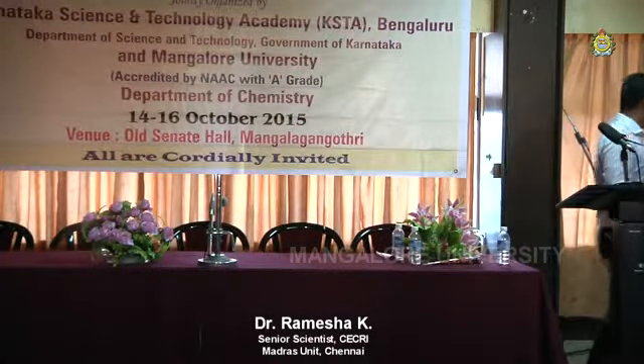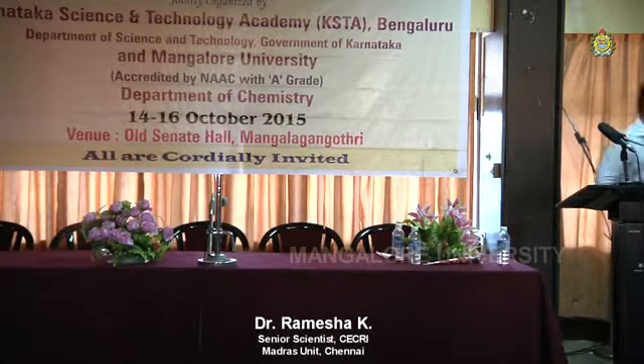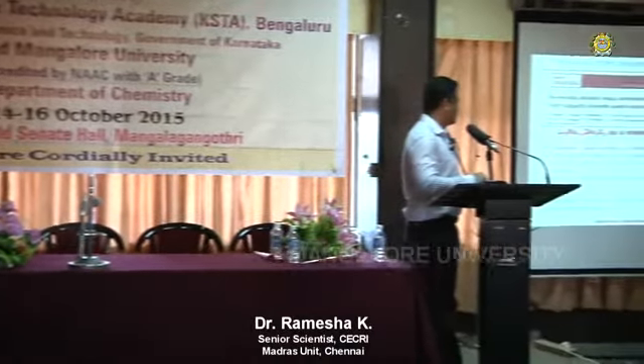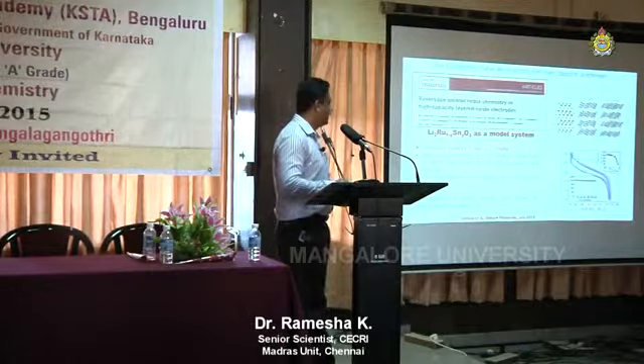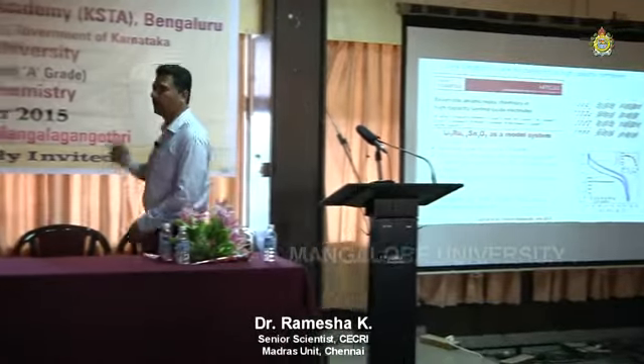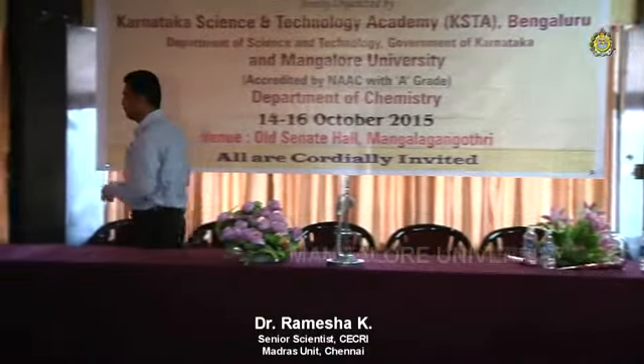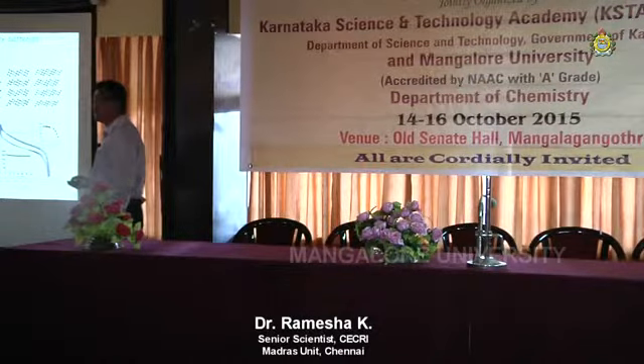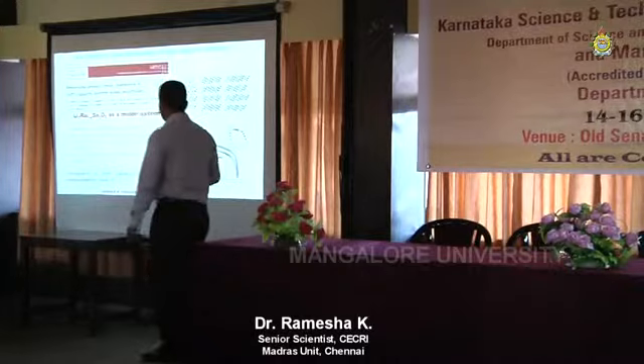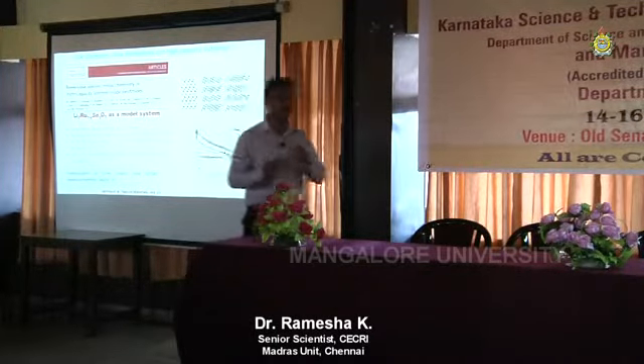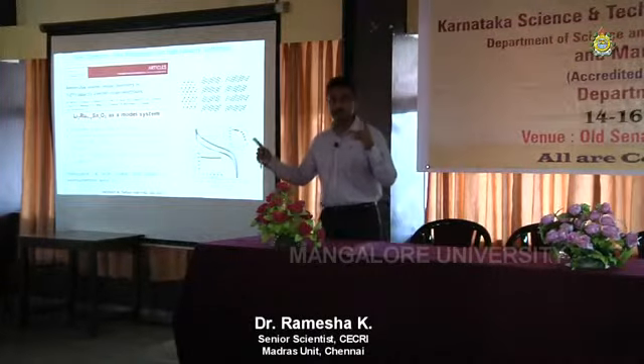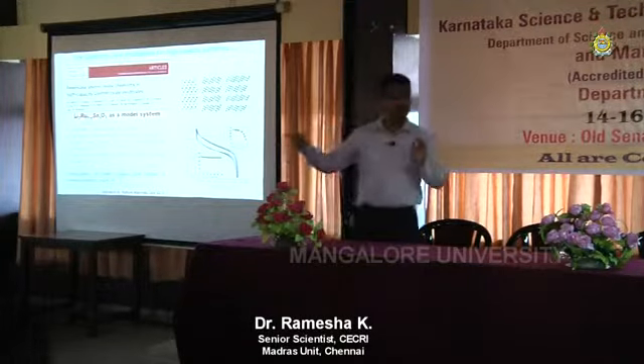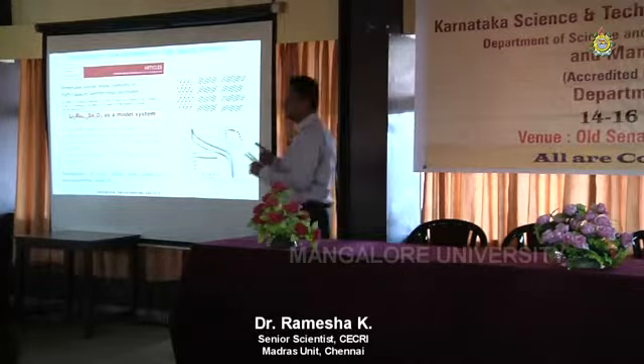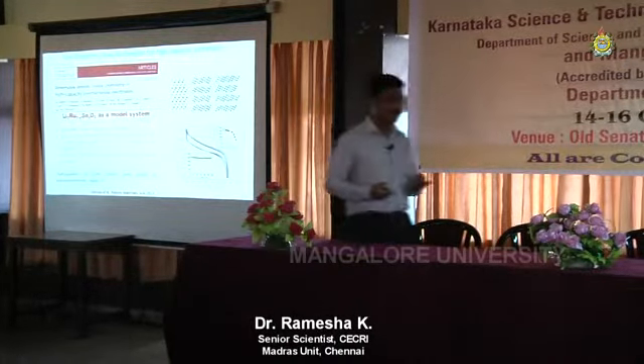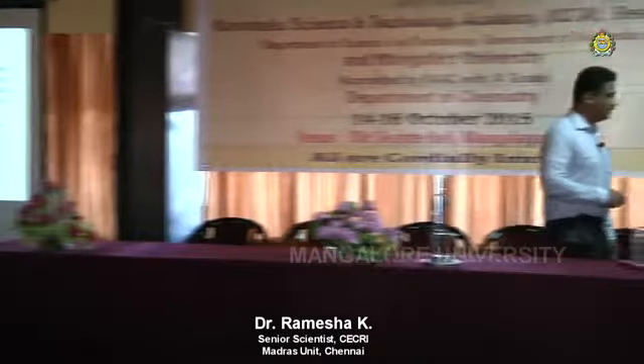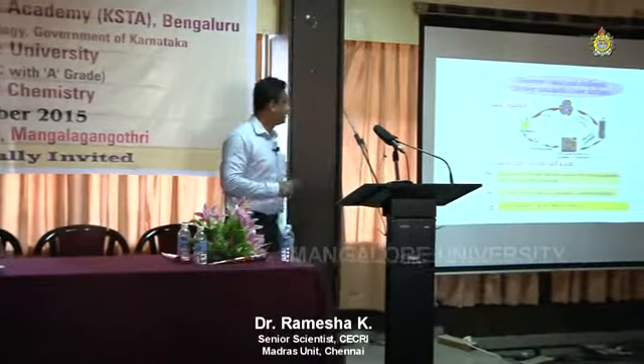We showed for the first time here that it's not only the inorganic material or any metal there, the oxygen of the electrode also gets oxidized and reduced. So this is what I am trying to tell you in a very simple way. In addition to these transition metals, with the cobalt ion getting oxidized and reduced, the oxide ion in the lattice is also getting oxidized and reduced simultaneously. So you have two candidates, ruthenium or tin. In addition to that, you also have the oxygen ion, which also gets oxidized and reduced simultaneously. So now the capacity is doubled. So this is a new mechanism which we showed in 2013, which was accepted in Nature.